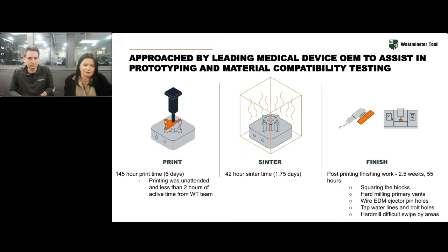What did we do to the blocks after they were printed? Well, one thing that we always do is square the blocks. So we always leave additional stock around the perimeter, and we are squaring that up either by grind or in hard mill. We were hard milling our primary vents, depending on what the tolerances of those are. A lot of times we're putting those in afterwards. We wire EDM'd our ejector pinholes. We tapped our water lines and bolt holes. And based on the CMM data, we looked at shutoff areas that we were concerned about, and we did some hard mill in those areas to get a strong shutoff.